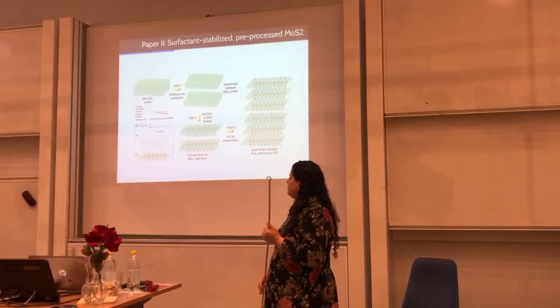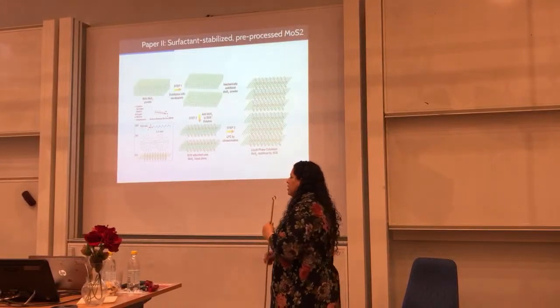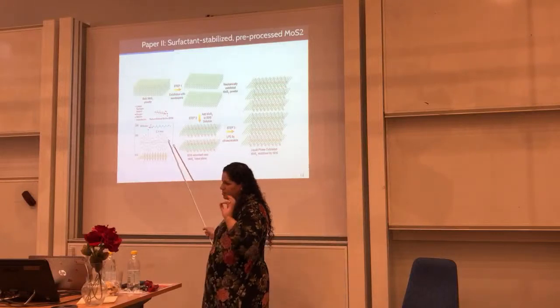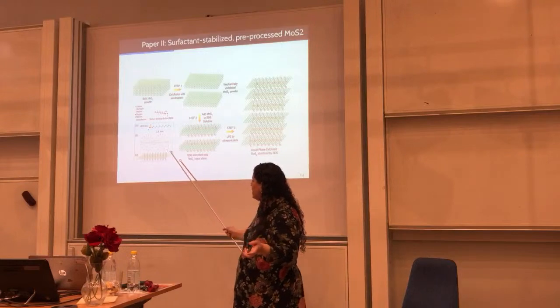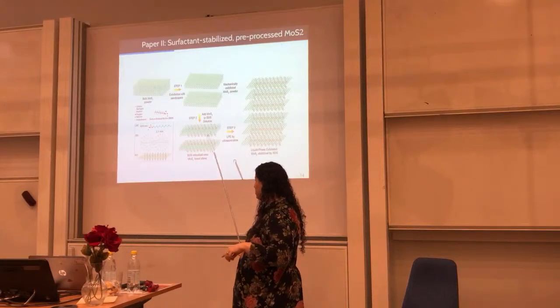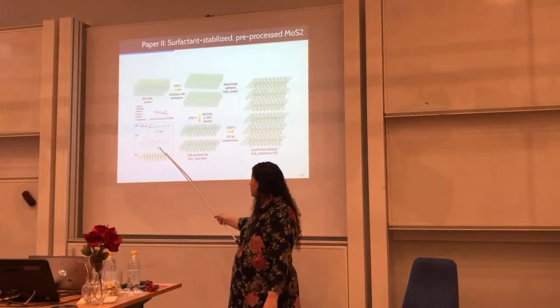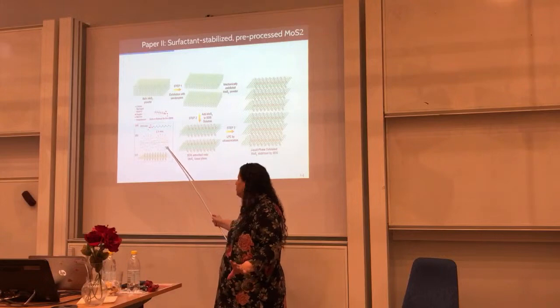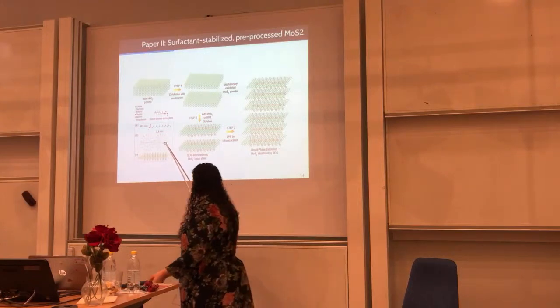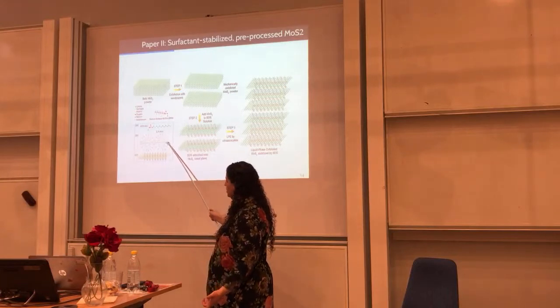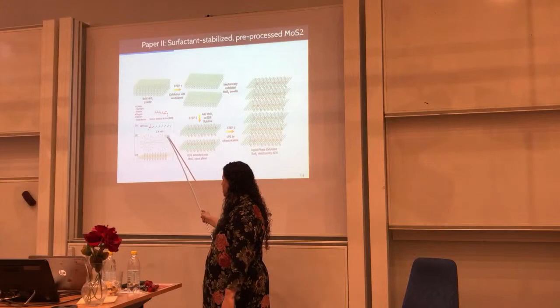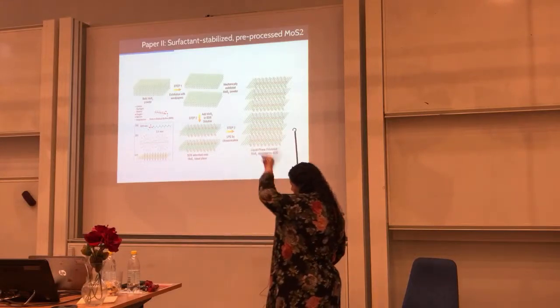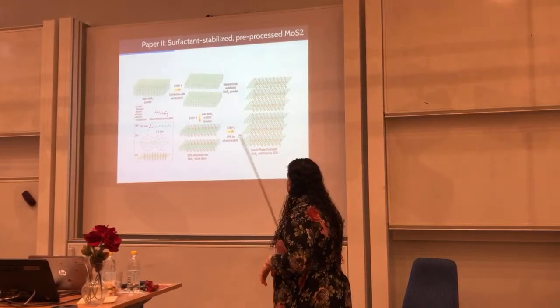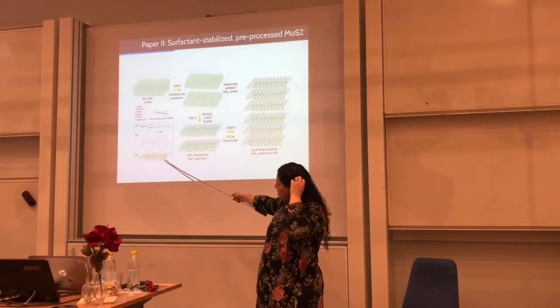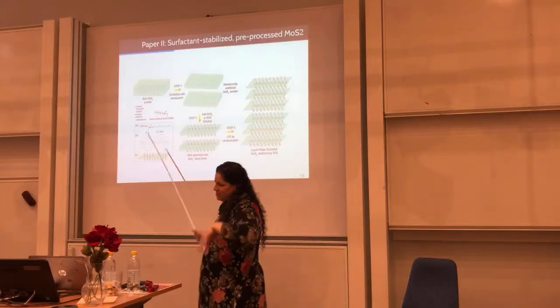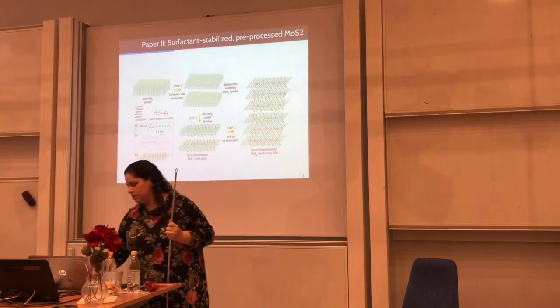There has been work in the literature that measured how the adsorption of the surfactant SDS happens on platelets like molybdenum disulfide, and they form a semi-micelle, which means that the hydrophobic part of the surfactant adheres to the hydrophobic surface of the molybdenum, and the hydrophilic parts of the surfactants, the heads, are in the solution. It would be very hard to draw like this, so I just did a simplification. I drew just one molecule, but it's just for illustration, so you understand.